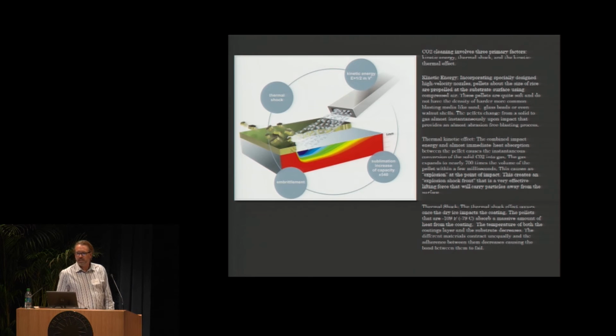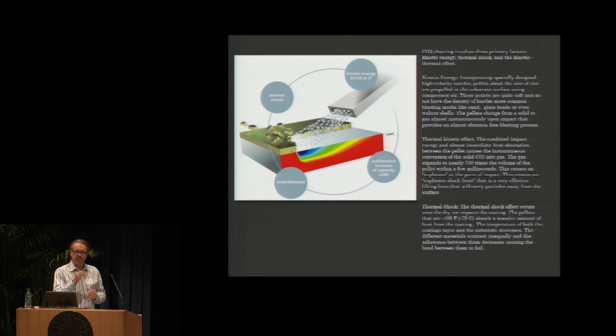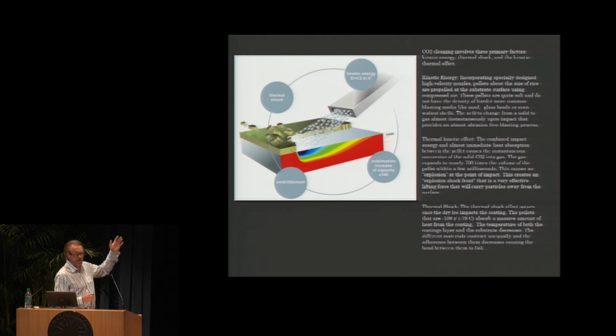I stole this slide, I think, from the last presentation, so this is awesome. I like to consider this working on 3 different effects, and we've had this discussed already, but there's basically the kinetic energy. This is what I like to think of as the pellet actually impacting the surface and what that can do. That in turn feeds the thermal kinetic effect, which is basically the pellet sublimating. As they do that, they expand upwards of, say, 700 times their size. So you get these kind of mini shocks to the system. And then you get the thermal shock, which can cause embrittlement of coatings. So we found that these are kind of the three primary actions happening.